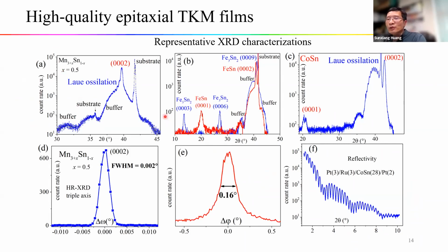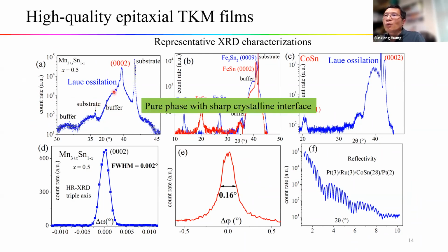So we have managed to grow high quality epitaxial films for all these four materials mentioned. The 2theta-omega scan in the first panel shows a strong diffraction peak without noticeable impurity peaks. In addition, we see the thickness oscillation along the main peak. This indicates the sharp crystalline interface in the films.